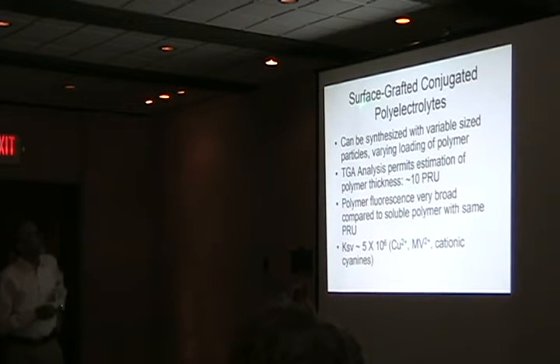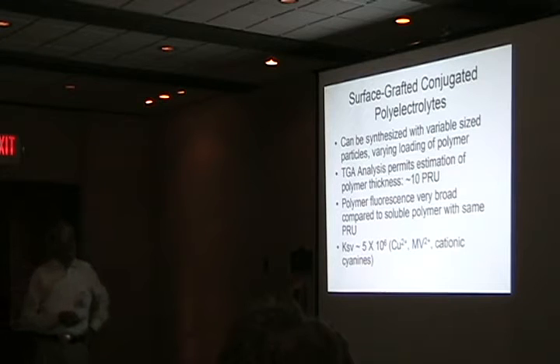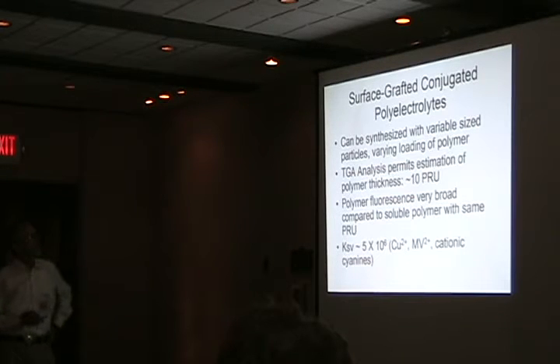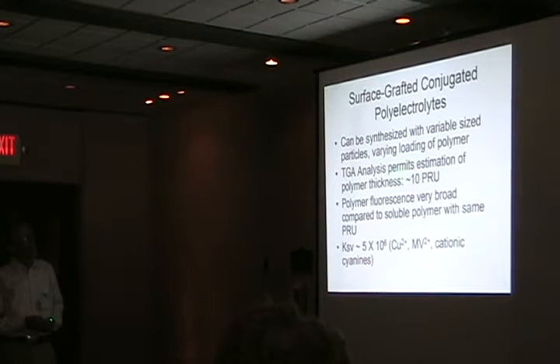So we can make these surface grafted conjugated polyelectrolytes. You can use various size polymers, various size particles, and you can vary the loading of the polymer. Now, in the one that we've worked with, and I'll show you results with in just a second, we've estimated by thermogravimetric analysis that about 16% of the material of one of these beads is polymer. And we've been able to assert that this is probably around 10 polymer repeat units. It's about 12 nanometers thick.